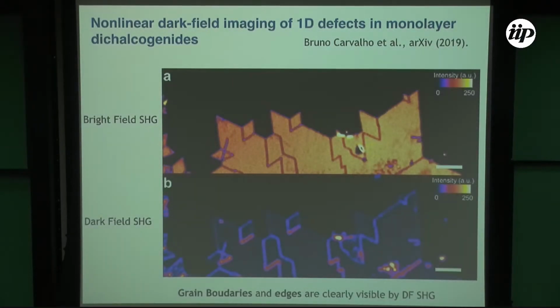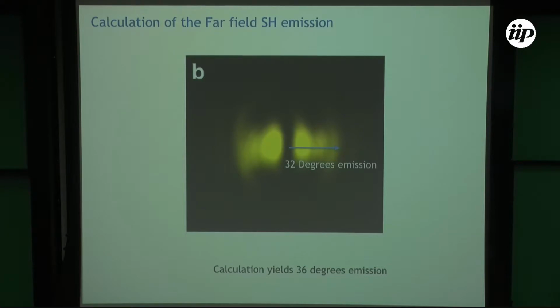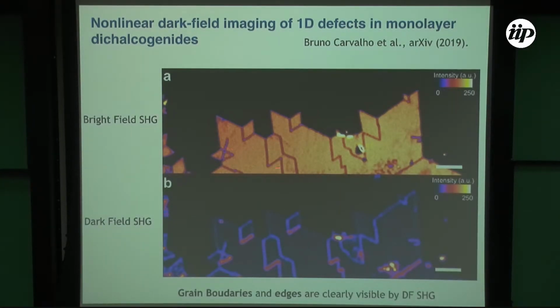Then what we decided to do is what we call dark field second harmonic imaging. Basically, we block the emission that is coming with a small angle and only collect light that is being emitted with a large angle. So this will be the bright field second harmonic: you have the bulk emission, and you don't have the grain boundary emission. But when you do the dark field second harmonic, you start to see the second harmonic coming from the grain boundaries, and also from the edges. So with this kind of measurement, we can directly determine where the grain boundaries are on the samples.